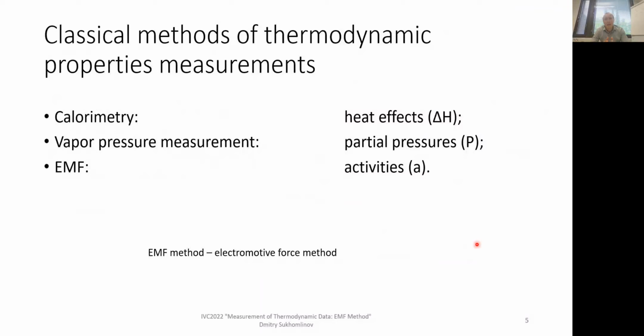There are three classical methods of thermodynamic properties measurements. It's calorimetric methods: differential scanning calorimetry, drop calorimetry, other calorimetric methods, and the primary data measured by this technique is various heat effects. Heat of fusion, for instance. And that's why calorimetry is at least believed to be superior for that, because these heat effects are measured directly.